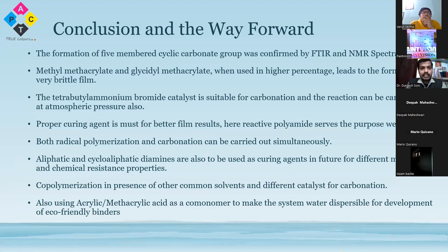Some catalysts like tetrabutyl ammonium bromide and methyl triphenyl phosphonium iodide are very suitable catalysts for converting the epoxy group into the cyclic carbonate group. Also, this reaction can be performed at atmospheric pressure. The second conclusion was that radical polymerization and this carbonation of the glycidyl methacrylate can both be carried out simultaneously. There is no need to do it in two steps. So it is an in situ process.